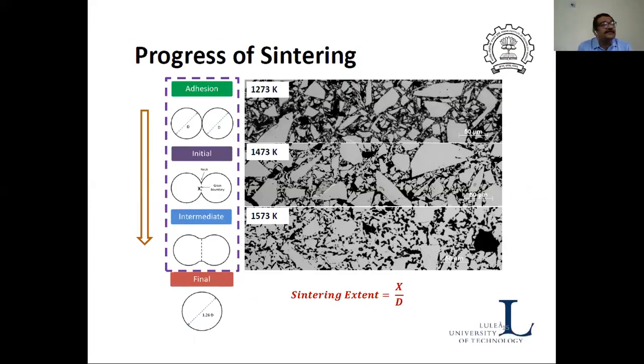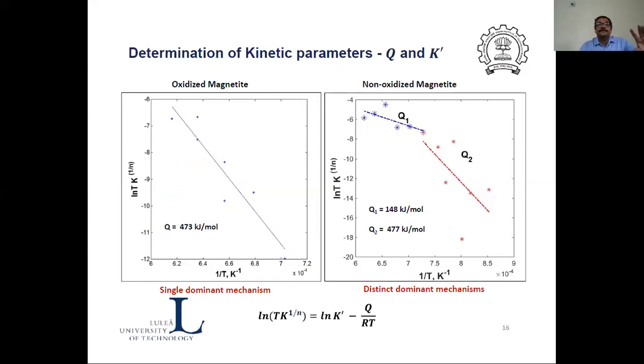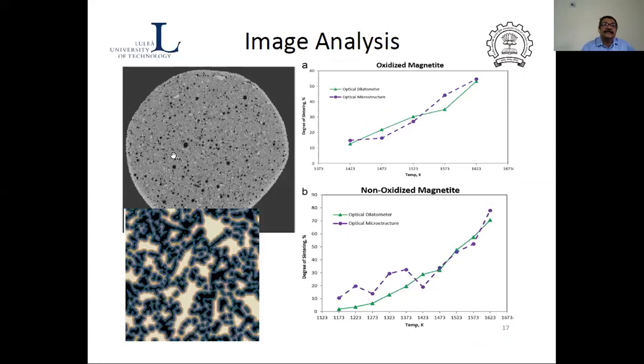Of course, we also analyzed the microstructure and all those things. As I was telling you, this is the neck formation in sintering, which is well known in powder metallurgy. So we analyzed the microstructure, looking for bridges. We had a collaboration with a computer science professor who works in image processing. For example, this is the image of a single pellet, but actually this is not one image. This is several thousands of images stitched together, and we have obtained the whole picture. And from this picture, again looking at the bridging, using image processing, one can also find out what the sintering degree is.